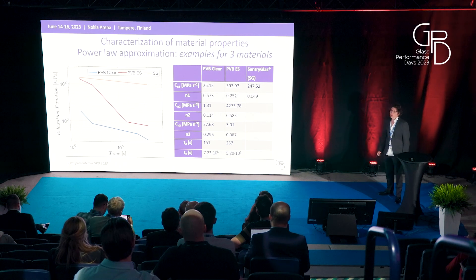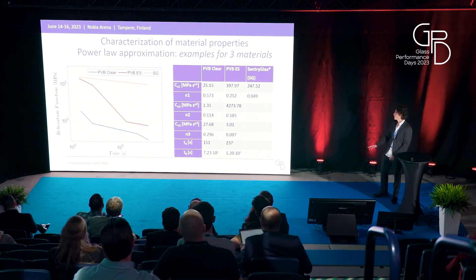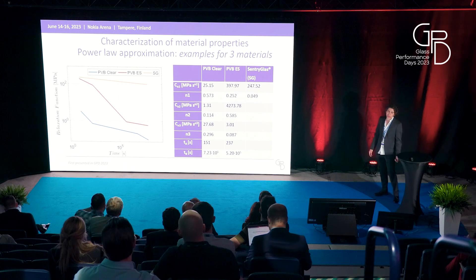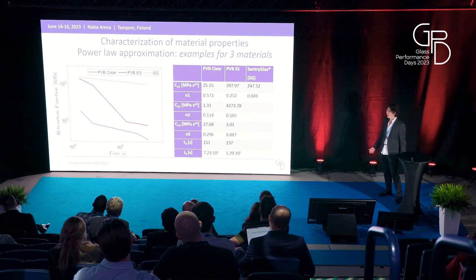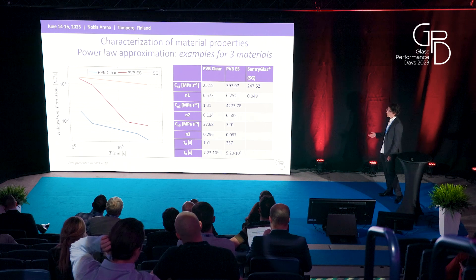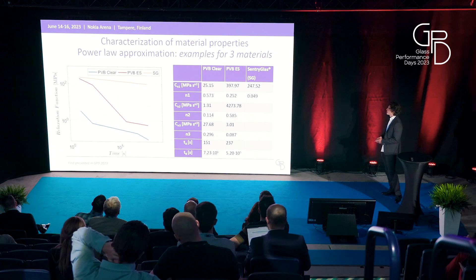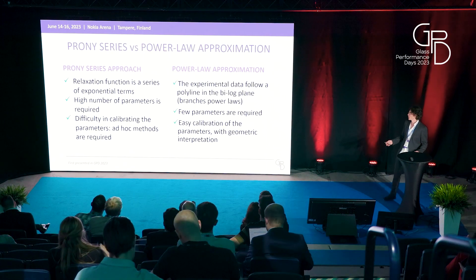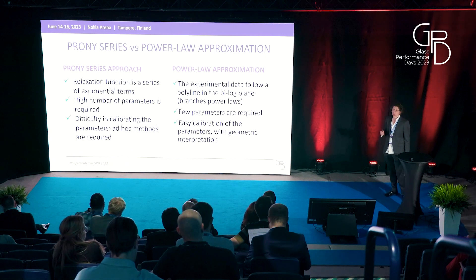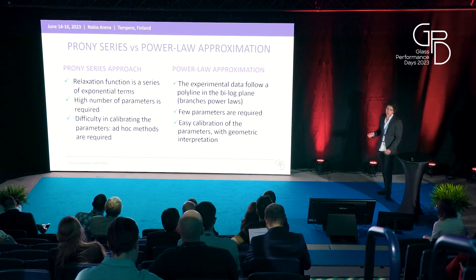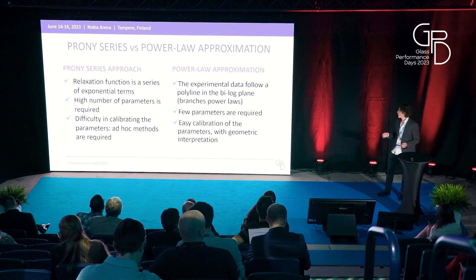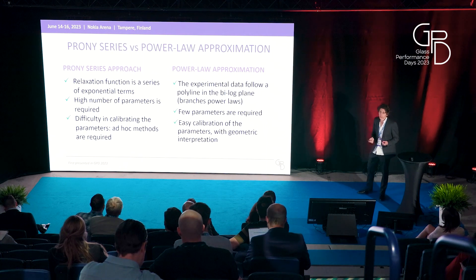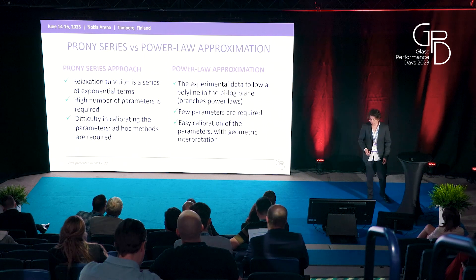Here is an example showing three different relaxation functions for three different polymeric interlayers: PVBClear, PVB ES, and SG, along with their parameter values. We can notice that not every relaxation function needs a piecewise power law — for example, SG only needs one power law. In brief comparison, the first great advantage of the power law over the Prony series is that experimental data are well fitted; second, fewer parameters are needed; and third, they are easier to calibrate.